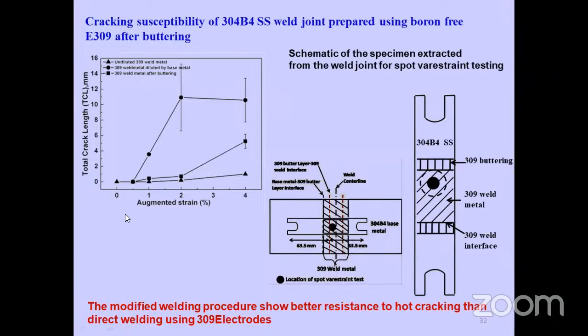So there we tested and we found that the results showed a significant decrease in the hot cracking sensitivity in the material. This curve shows the susceptibility of total crack length without using the buttering layer. And this is for the nil dilution, that is at the center where there is no base metal dilution. And this is after buttering. We have seen that there is a sufficient decrease in the cracking susceptibility in the weld joint.